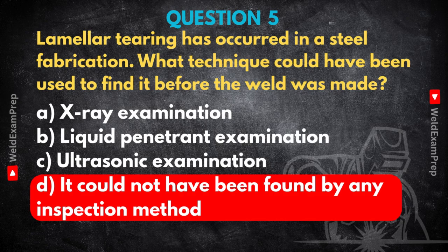Exactly. It's caused by the shrinkage stresses from the cooling weld metal pulling on the base material in the through thickness direction, what we call the Z direction. Okay. Pulling perpendicular to the plate surface. Right. And if the steel has poor ductility in that direction, often because of elongated inclusions or impurities lined up from the rolling process, it can't stretch, so it tears. Precisely. It tears internally, usually in steps, parallel to the rolled surface.